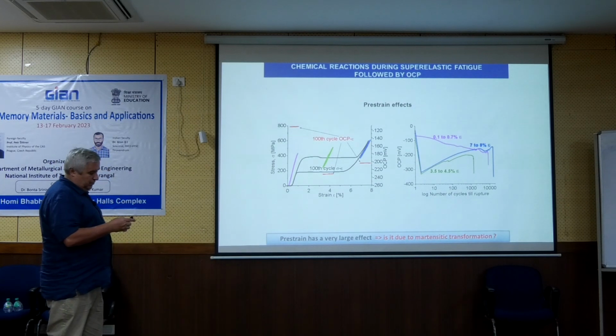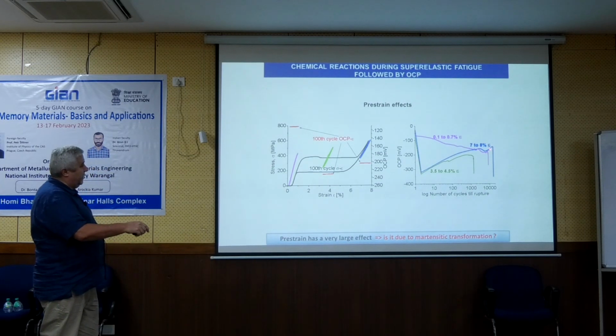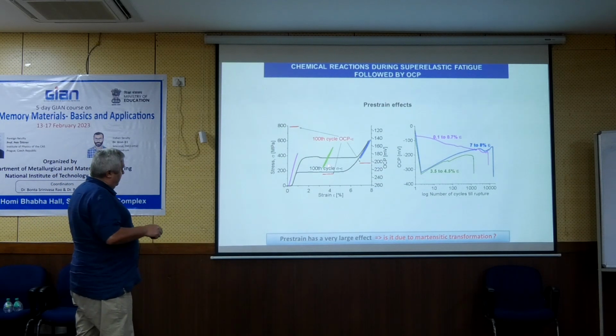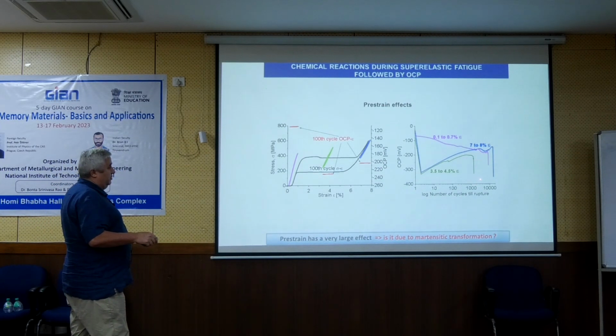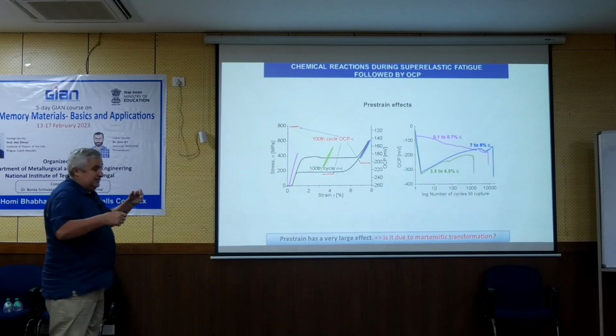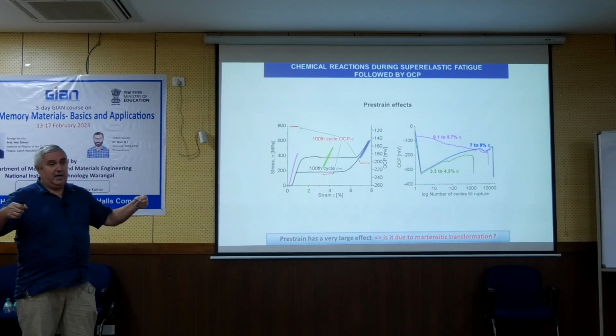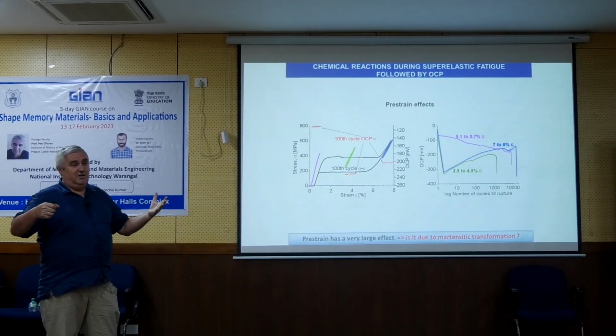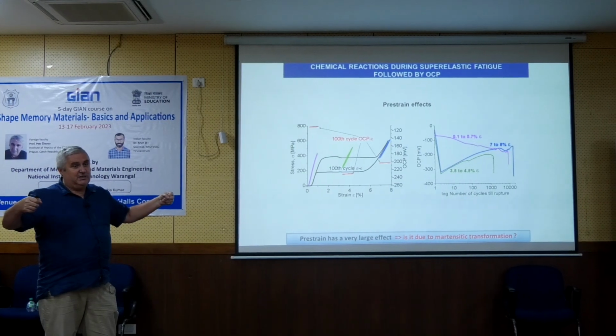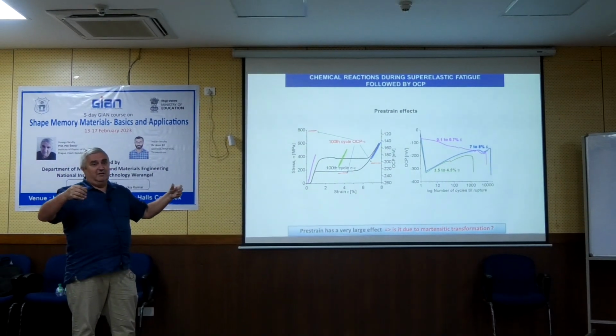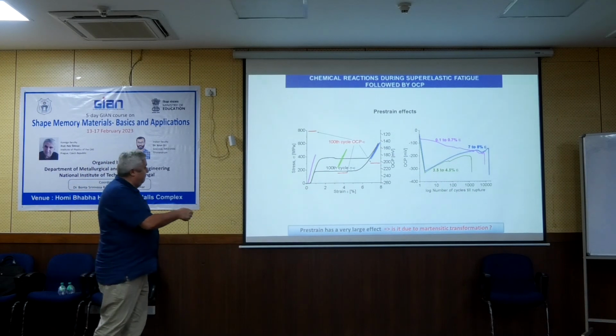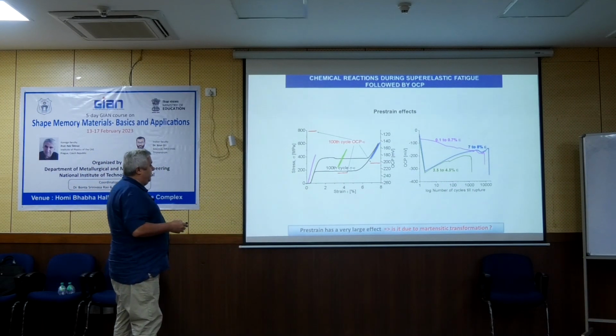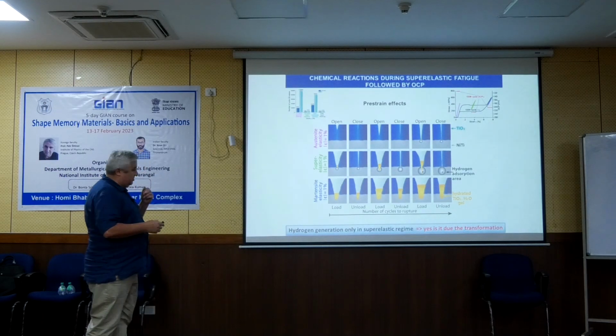So in that case, the long life was maximum. This is in logarithmic scale, so something like 30,000. And in the middle, there are only 1,000. So 30 times higher life in martensite state, where the stress is larger and amplitude is also large. So it's very counterintuitive. You have the wire, you have large pre-strain, large amplitude, and long life, and then you have here short life. So why is that? Well, it is shown here.